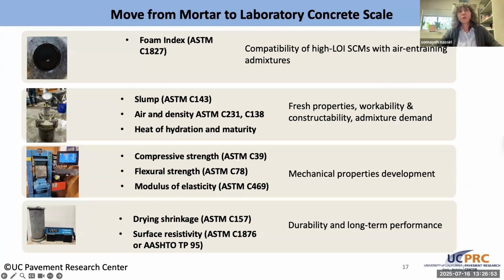Foam index is something that, okay, so then we finished that first round of the screening, and everything checks out, now we are scaling up already from about a bucket or a couple of buckets of the material. So we are working with the supplier at this point to scale up with them, and we're trial batching concrete at this point. For the materials that are maybe higher in carbon content or organic matter, we want to look at compatibility with air entraining admixtures for freeze-thaw durability.